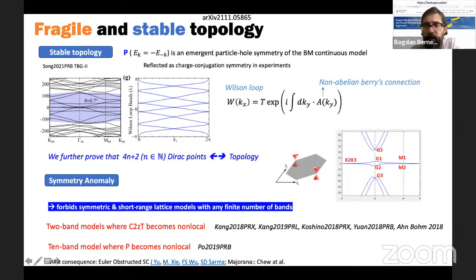Now, I don't want to go a lot into it, but it turns out that the model is even more special in the sense that it has an interesting stable topology. It's actually topological at any bandwidth. So not only taking these lowest bands; this is the same thing plotted on a much larger energy scale, same band structure. These are the flat bands here. If I try to see if these two flat bands are topological, we already proved it. Their eigenvalues don't match any atomic limit, hence they have to be topological.